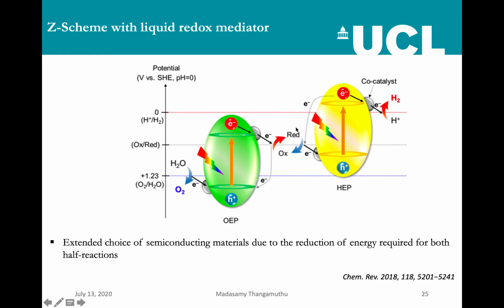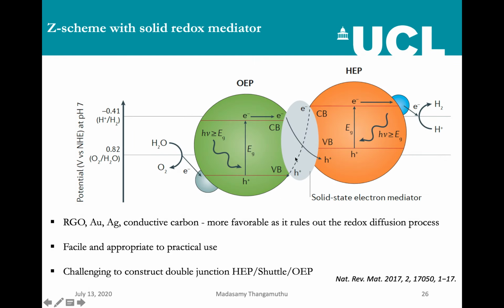If we change this solution redox mediator, that is the second system with the solid redox mediator here. So one can use gold, silver, or conductive carbon or reduced graphene oxide as a solid redox mediator in Z scheme. And this is more favorable compared to the liquid redox mediator Z scheme, because it can really rule out the redox mediator ion diffusion, which probably causes some interference with the adsorption of water molecules on the surface of the photocatalyst. We believe that this is more facile compared to liquid redox mediator and more appropriate for practical use.